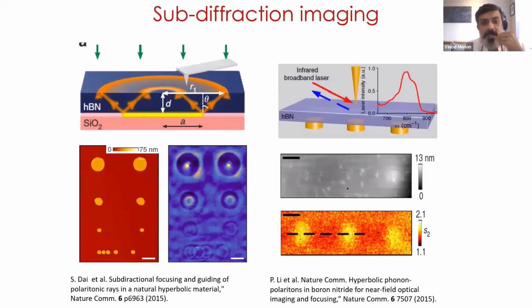So again, the other intriguing property is that because these have hyperbolic dispersion, you can look at these systems in the subdiffraction limit. So you can see here that these disks are much smaller than the wavelength of light that you're looking at. Despite that, you can actually see these things when you excite the phonon polaritons because of this trajectory of the rays that happen in these systems, and you can break the diffraction limit.